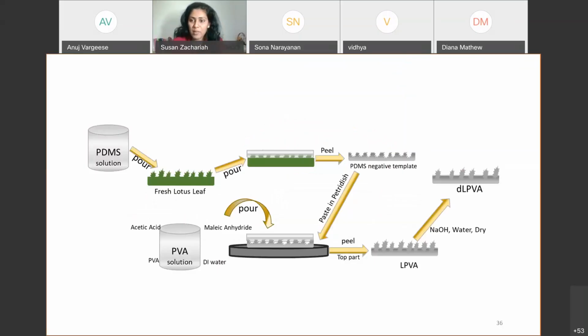Same as the first experiment, we have taken the lotus leaf and poured the PDMS over it. After solidifying, the PDMS is peeled out so that it has the complementary patterns of the lotus leaf. Then this is placed and stuck on a glass plate. The PDMS with holes is placed on a glass plate. Over this, we have used PVA solution, and after it is heated, the PVA is peeled out, and we found the lotus pattern PVA has similar patterns to the lotus leaf.